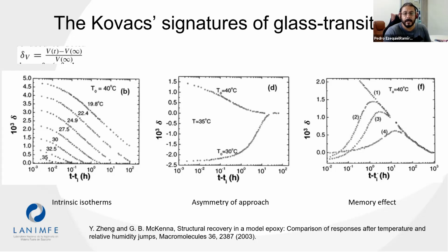One important point to highlight here is that the Kovacs signatures are also observed if we measure the so-called fictive temperature. Such a quantity is defined by comparing the time-dependent value of some thermodynamic property with the same value at equilibrium. For example, if I measure the specific volume at time t, obtaining the value V0, then I can search for the temperature at which the system has the same value V0 at equilibrium, let's say Tf. Thus, we can say that the non-equilibrium state at time t has a fictive temperature Tf. Please remember this quantity because I will return to it later.